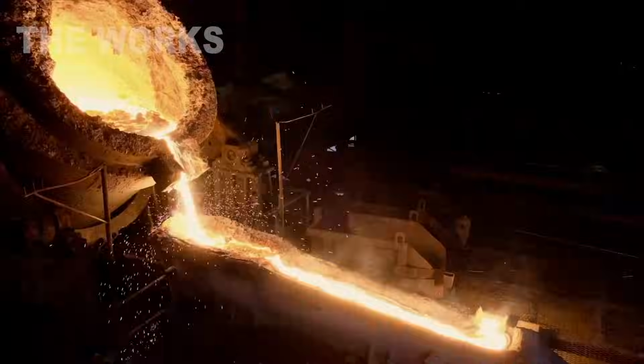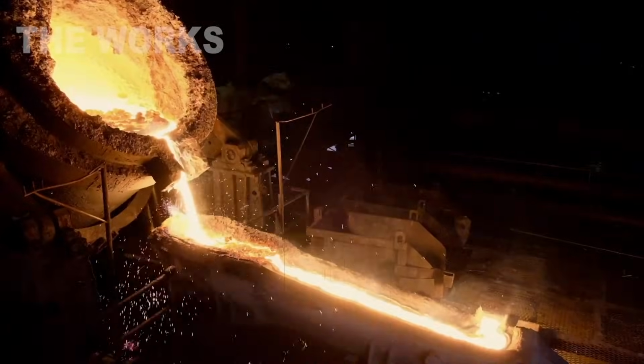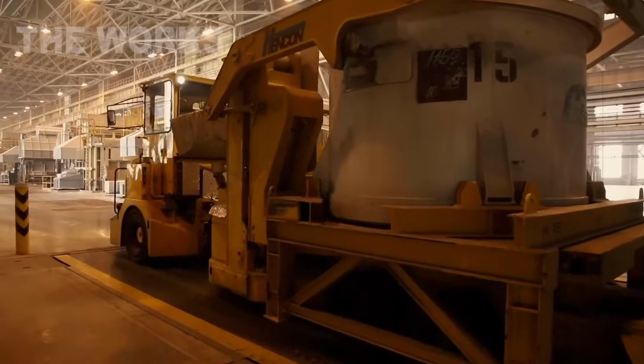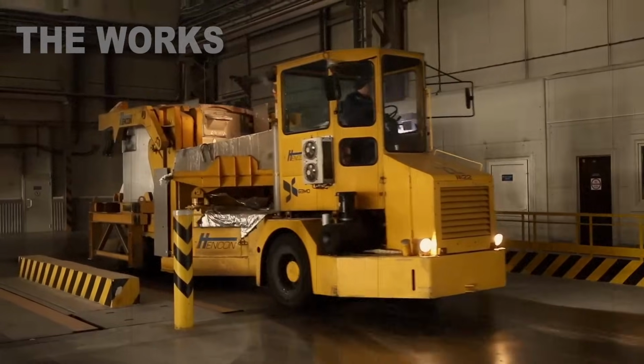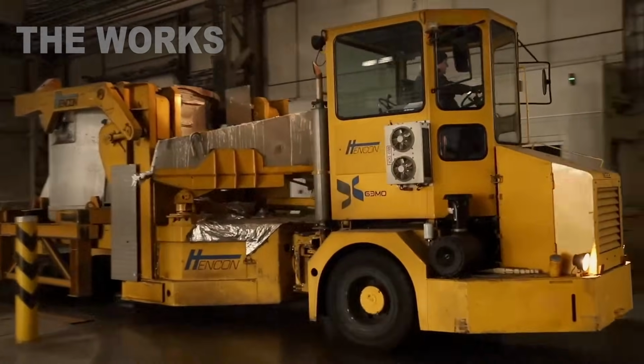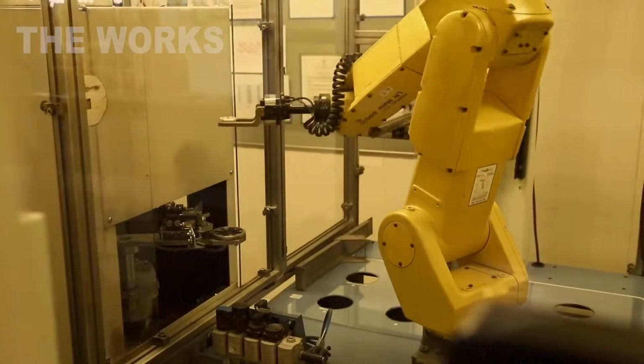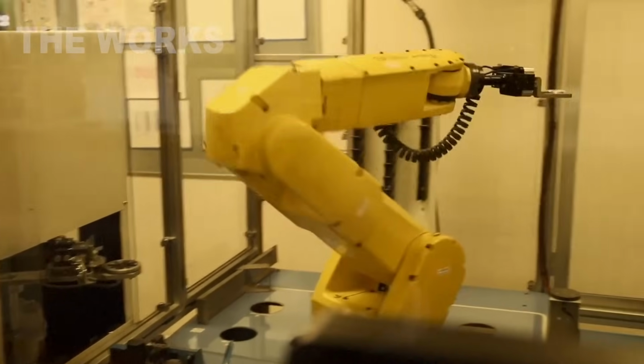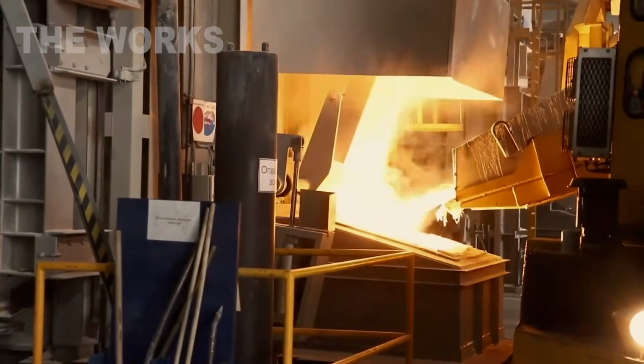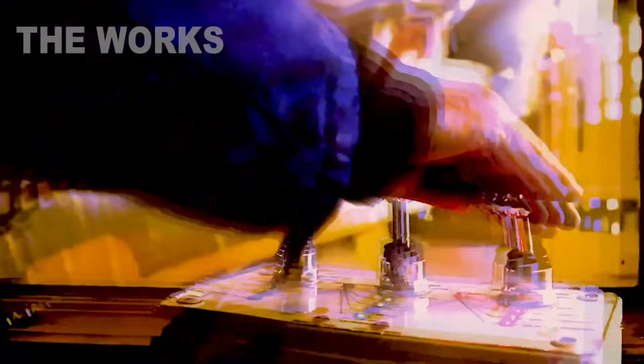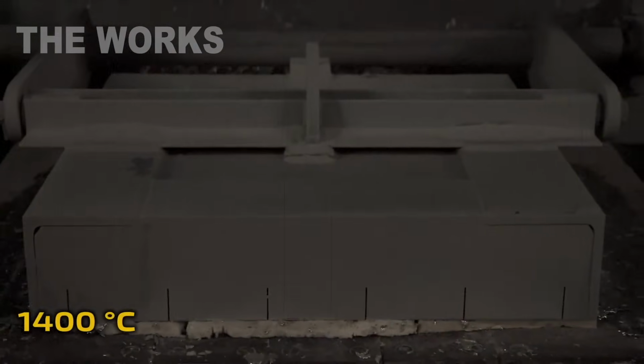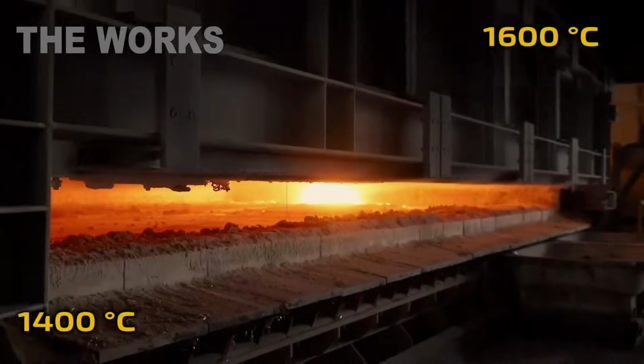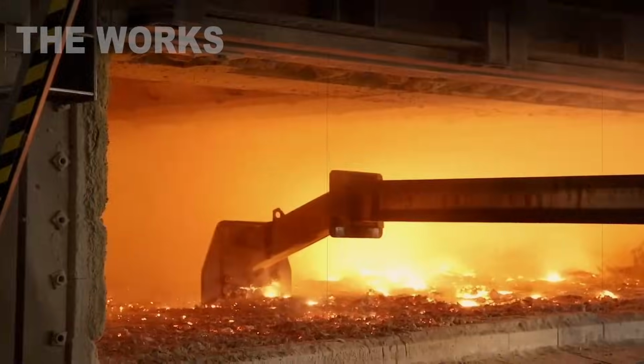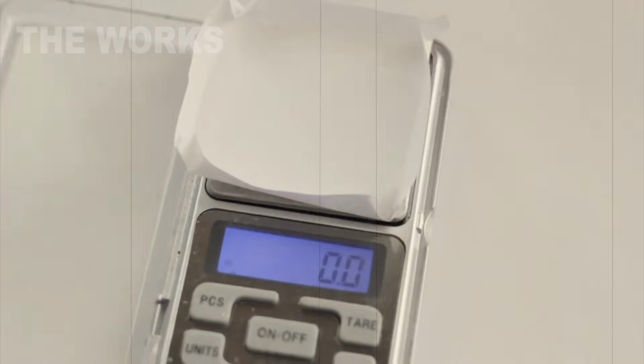One of the most critical applications is the production of hard alloys known as tungsten carbides. These alloys, combining tungsten with carbon, plus cobalt or nickel as a binding agent, rank among the hardest man-made materials. Tungsten carbide is created by heating tungsten powder with carbon at temperatures around 2500 to 2900 degrees Fahrenheit. Tungsten carbide crystals form, which are then ground into powder. This powder is mixed with cobalt or nickel, serving as a binder, pressed into molds, and sintered.